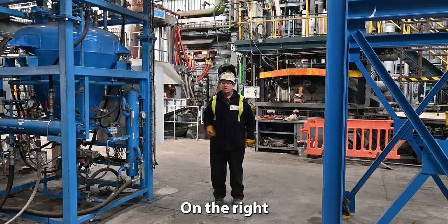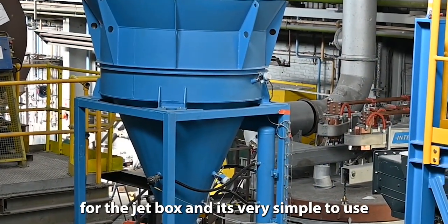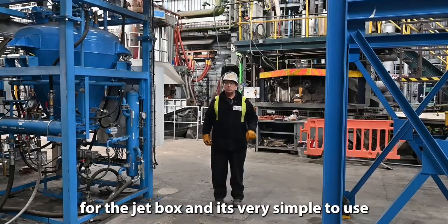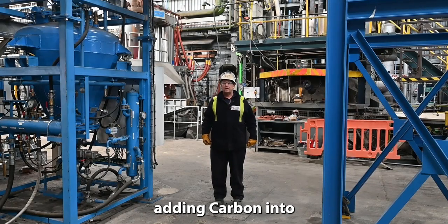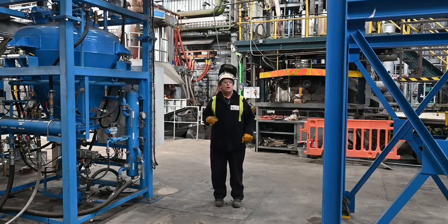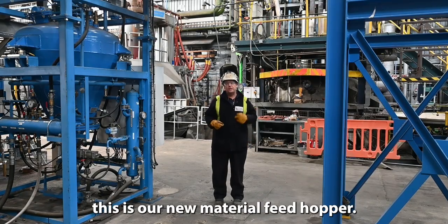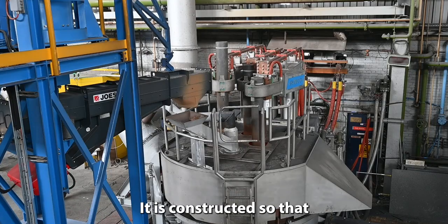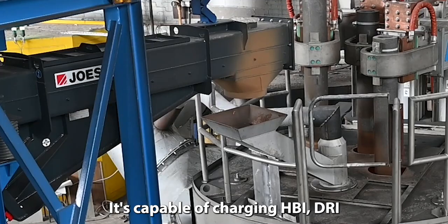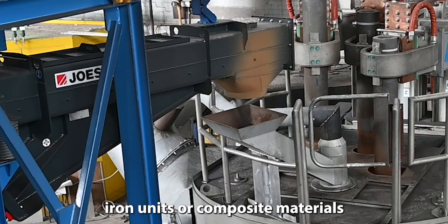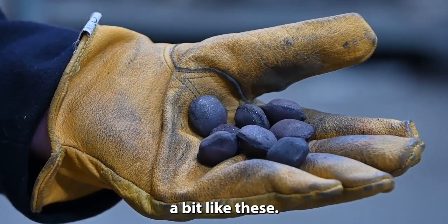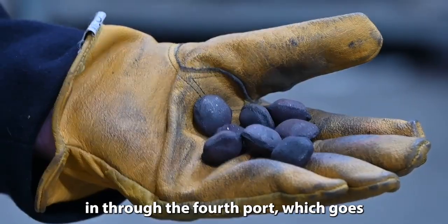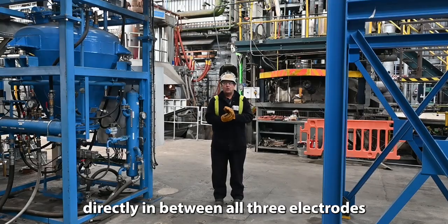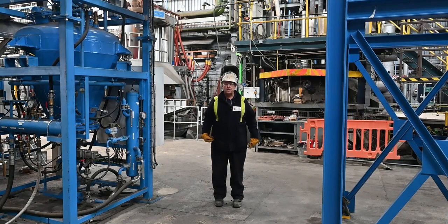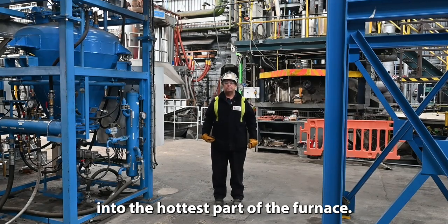On the right, we have the carbon feed hopper for the jet box. And it's very simple to use really in terms of actually adding carbon into the melt when required. On my left, this is our new material feed hopper then. It is constructed so that it's capable of charging HBI, DRI, iron units or composite materials, a bit like these, then in through the fourth port, which goes directly in between all three electrodes from the furnace roof into the hottest part of the furnace.